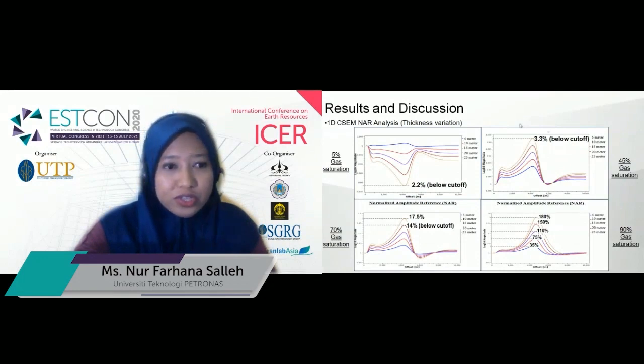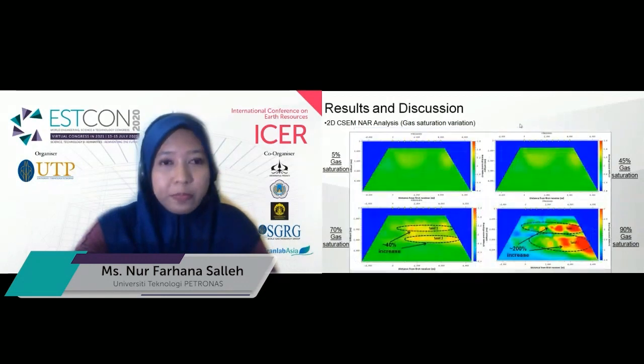So for 70% of gas, only the 25 meter thickness, which is the maximum thickness, has a response of more than 15%, which is around 17.5% response increase. And for 90% of gas, all the tested thicknesses already show very strong response. Even with 5 meter, the response increase is around 35%. So this is the result for our 2D CSEM.